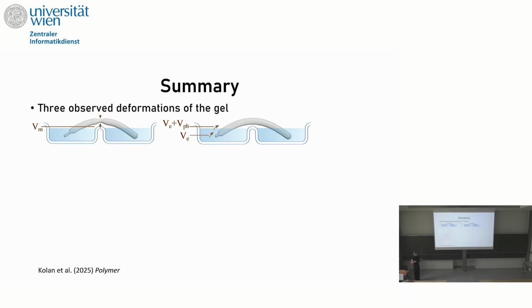So we conducted two control experiments. Putting a droplet of sodium chloride, the equilibrium solution, in this area exposed to air showed that this area doesn't shrink. So it's due to evaporation of water and not related to the calcium cations.